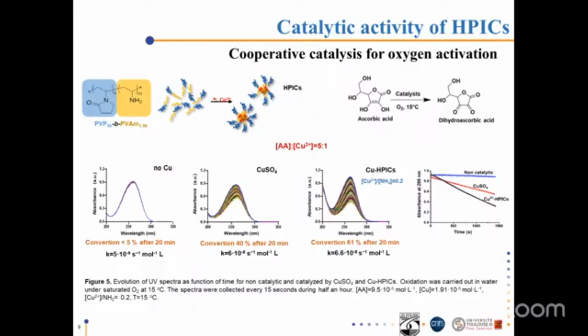The oxidation was faster in the presence of copper sulfate, with a conversion equal to 40%, and the complexation of copper ions within the HPICs enabled us to reach a conversion of 61% after 20 minutes for a ratio 0.2. Therefore, copper HPICs seem to positively influence the ascorbic acid oxidation process. This naturally leads to the question: what is responsible for this effect? Is it the special colloidal structure of HPICs, or is it simply due to copper complexation?